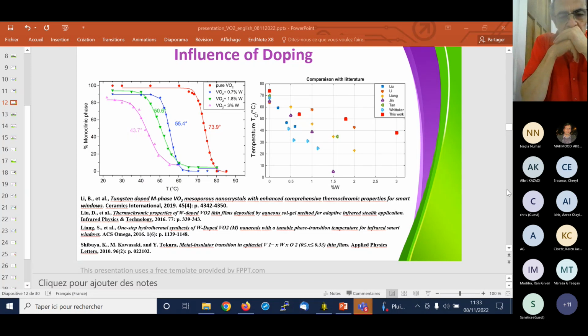But as I was saying, I was unable to see any specific signature of the tungsten in the diffraction pattern. So in my opinion, it means that the tungsten was distributed quite uniformly inside the film. Maybe there were some clusters, but very small ones, so that you could not see them on the scattering pattern. Because if they are very small, the Bragg peak of the tungsten would be extremely broad, and we didn't see anything like this.